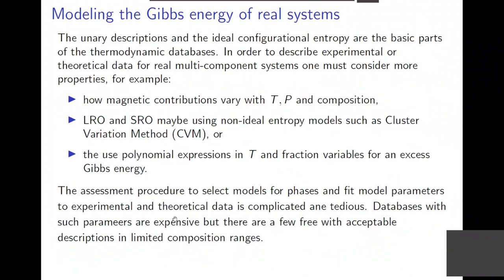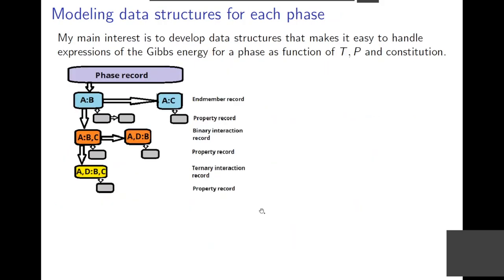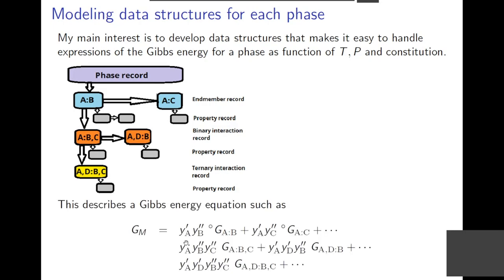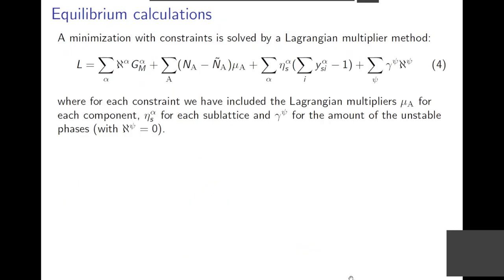And the parameters in those databases are fitted to experimental data and also to what you can theoretically assume for a phase. And my interest in this is to develop database software. So one has to record the Gibbs energy expression for the different phases, and with a data structure like this, one can describe the polynomial expression quite well. And then you can add a magnetic contribution, and one can add a configurational entropy contribution. So this is the basic expression describing the different phases in the system.